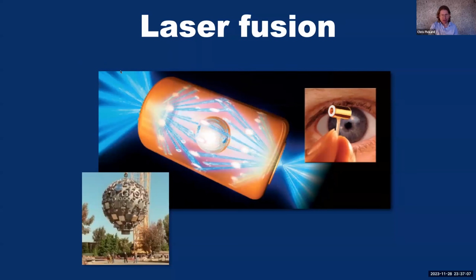So the basic experiment that's done is you have a pellet of carbon held in the center of a gold can. In the center of that pellet is the fuel, and then you fire many very high power lasers into the gold can, which then interacts with the gold and generates X-rays, and those X-rays bathe the outside of the pellet with intense radiation. And then that material starts to ablate off in a spherical way, and you end up with a spherical rocket all heading towards the center of the pellet, and hence high compression.